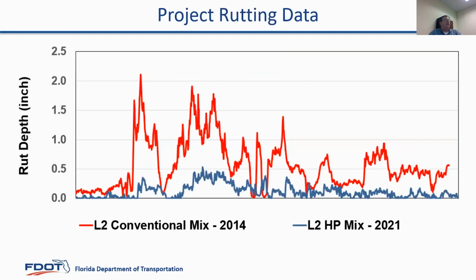So what this chart shows is the performance. The red plot there is the laser profiler rut data before the interim project was done. And you can see the laser profiler is showing rutting in excess of 2 inches right there, and then a lot of high rutting in other places. The district engineer out there told me at one place they were close to 2.5 inches of rutting with a hand measurement. So again, a lot of rutting, and then they laid the HiMA mix, and you can see the blue plot is after 6 years of traffic, and we had 6 really hot summers too, and you can see that the rutting is significantly reduced throughout the corridor with a single lift of high polymer binder. So you're definitely getting the value there you want.